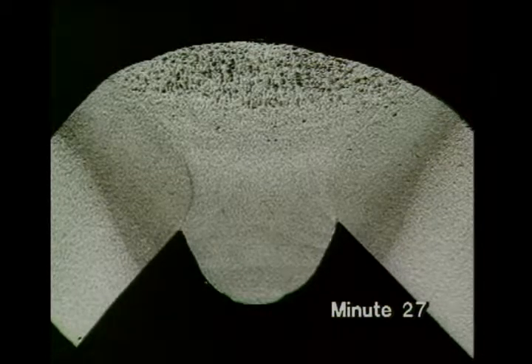This, on the other hand, had the plates overlapping before welding, and the weld hasn't penetrated right through the joint. Here, the gap was too big, and the molten metal has penetrated too much. In fact, it could have melted right through and left a hole.